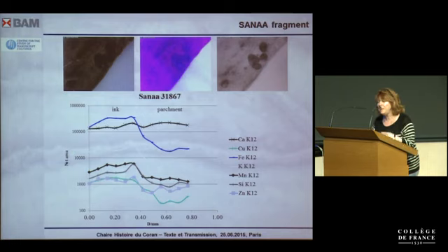Those elements, when they appear together with iron, indicate that in the basic recipe vitriol was used, and vitriol was a common ingredient of the iron gall inks. So in this very case, we would say this is not carbon ink, but this is not iron gall ink either, this is a mixed ink. And what we usually know about the inks from Arabic manuscripts is that a great number of mixed inks was used, which is very important.